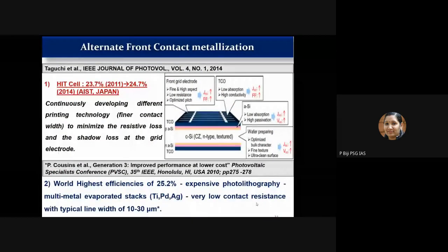As an alternative front contact metallization, some groups have reported TCO, transparent conducting oxide, because it is a transparent conductor. So obviously, you can expect the shading loss to be reduced. But the technology they were using was photolithography, so printing is very difficult in that case. The cost was very high, although the efficiency was very high.